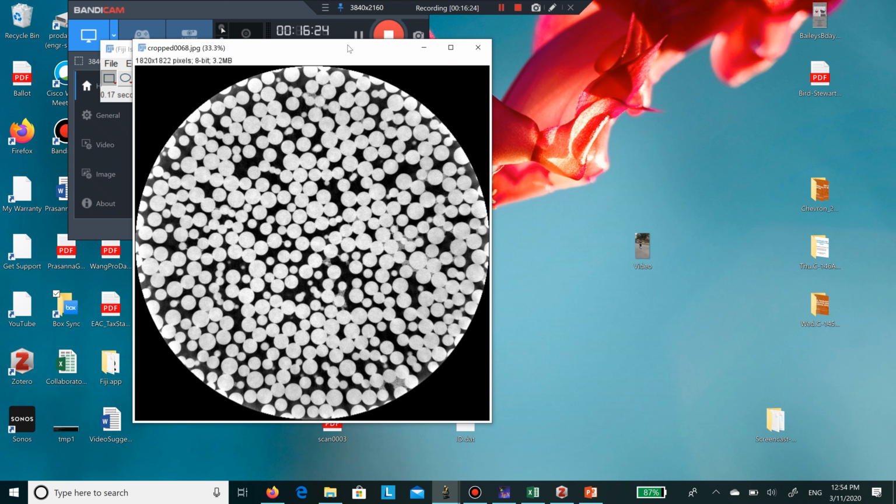But on the first look, it looks pretty clean. The beads are really nice and round. Our eyes are happy. This looks pretty. I do have something else going on. I have some microporosity, which is injected beads. So this is a sample that was exposed to a particulate flood of particles that are at least 20 to 40 times smaller. And then it was dried, and you're looking at the results.